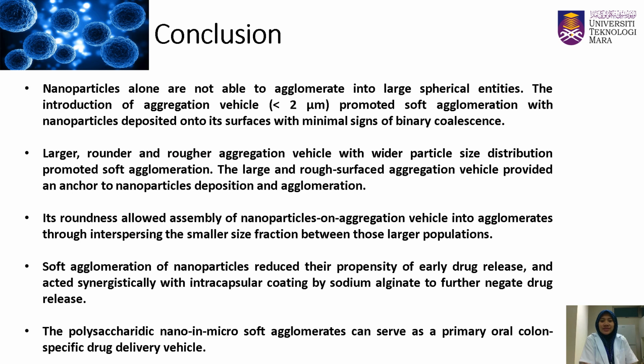For the conclusion, nanoparticles alone are not able to agglomerate into large spherical entities. The introduction of aggregation vehicles less than 2 micrometers promoted soft agglomeration with nanoparticles deposited onto their surfaces with minimal signs of binary coalescence. Larger, rounder and rougher aggregation vehicles with wider particle size distribution promoted soft agglomeration.